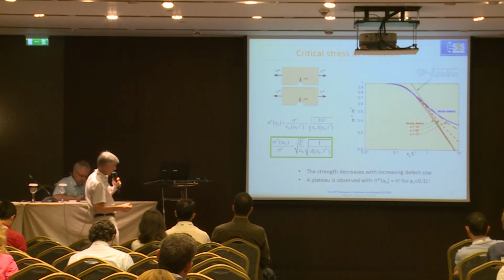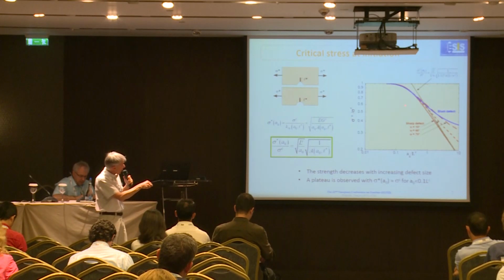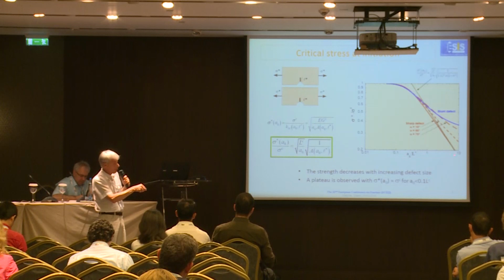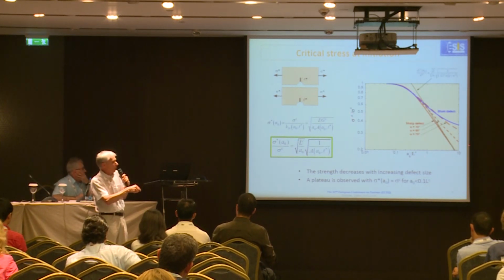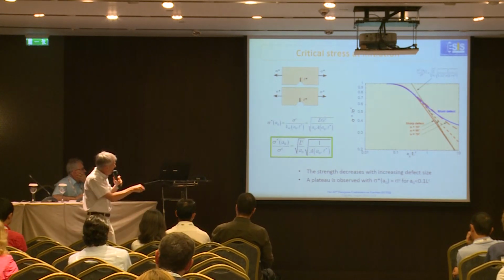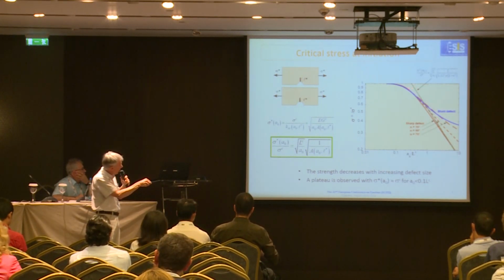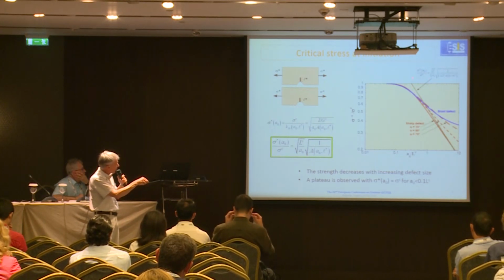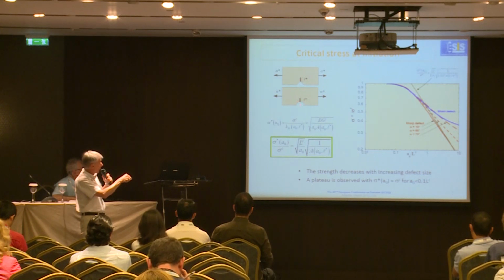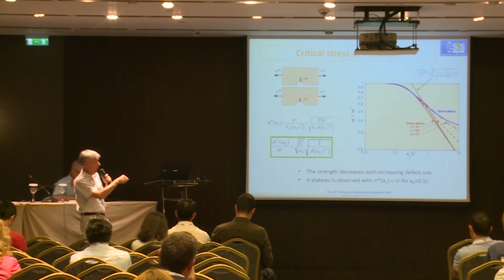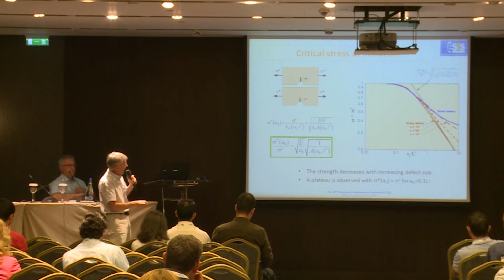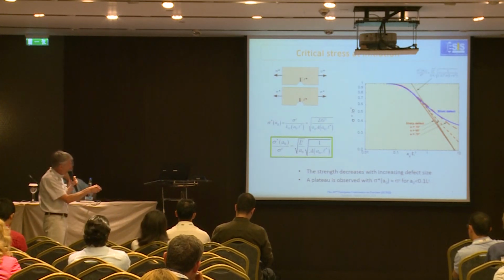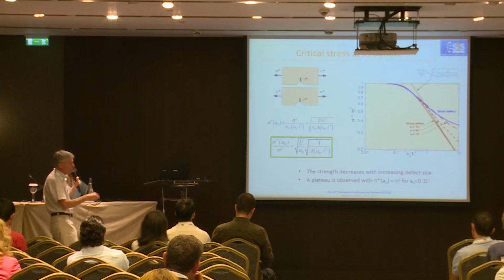Okay, this is the first interesting result. Of course, we have a decreasing function, as expected. If you increase the size of the defect, you decrease the strength of the material. And this black dotted line is obtained with the standard linear elastic fracture mechanics, assuming the flaw is a simple edge crack. Okay?